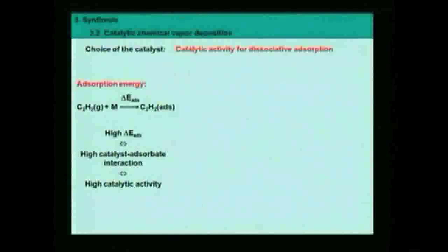How do those elements modify this activation barrier? Actually, you need to weaken the carbon-carbon bonds. And to do that, you need to create a very strong interaction between the adsorbed molecule and the surface of the catalyst. So the higher the interaction between the adsorbed molecule and the catalyst surface, the higher the catalytic activity, because you will weaken the CC bond by creating a very strong carbon-catalyst bond.